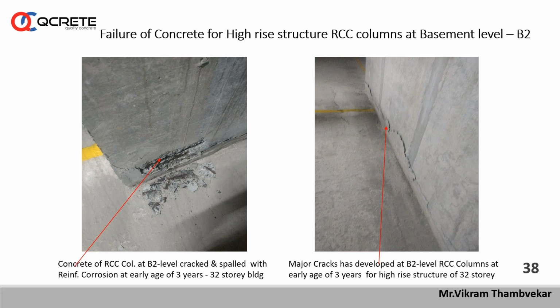Because when your formwork height is more, there are chances of making more and more honeycombs and more porosity, because even though care has been taken, compaction may not be done properly. So to avoid this, concreting for very tall formwork should preferably be 1 meter or 1.2 maximum, or 1.5 is the maximum, because I have seen many failures of columns because of this wrong practice. People are casting this 2.8 meter column straight away. So this is a wrong practice, and can be avoided.